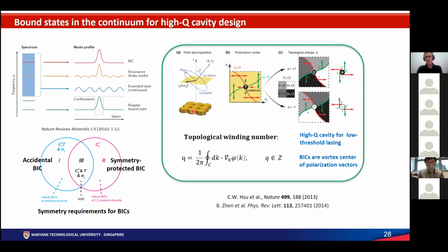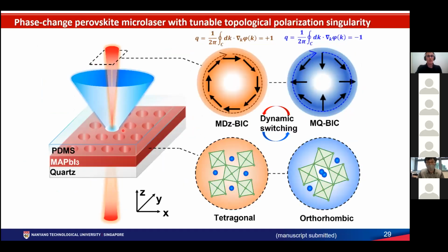The design we use has an in-plane inversion symmetry. And we realized it by nanoimprint lithography on a perovskite film of about 250 nanometers thick, which is embedded into a 1.5 refractive index platform. So when we excite with 405 nanometer laser light in the blue, we observe laser emission. And as you will see, this laser emission will have a clear topological winding number of 1.